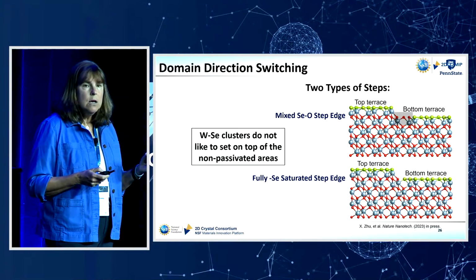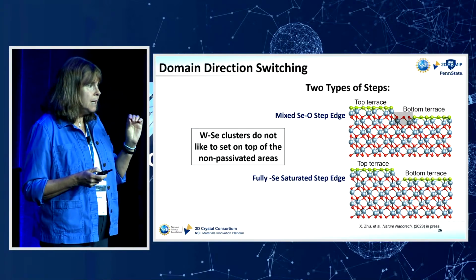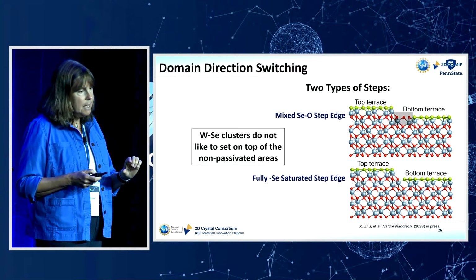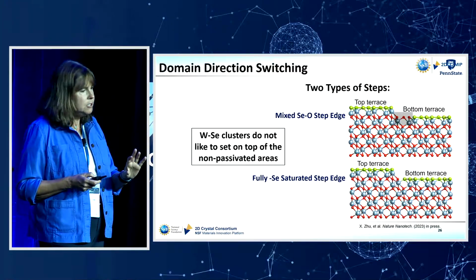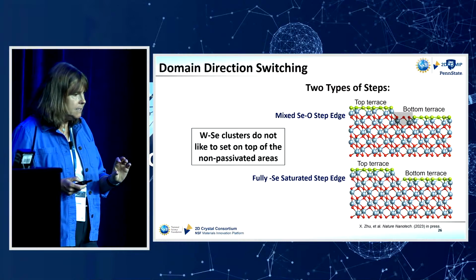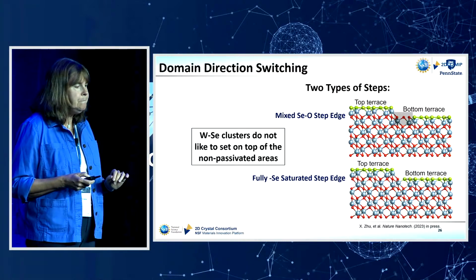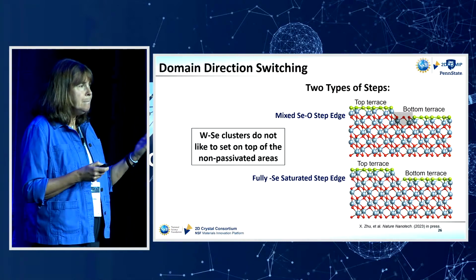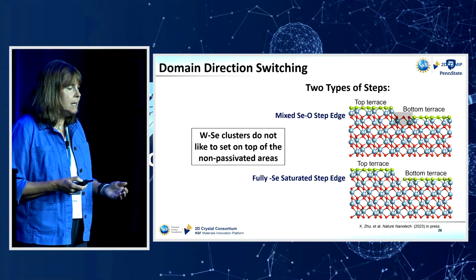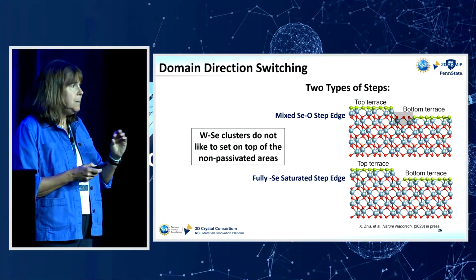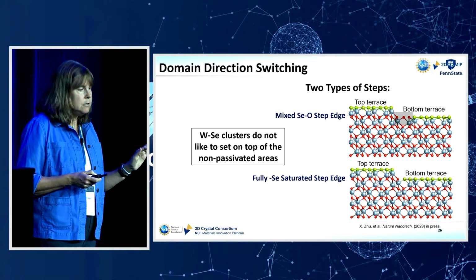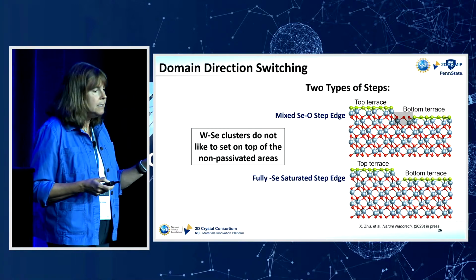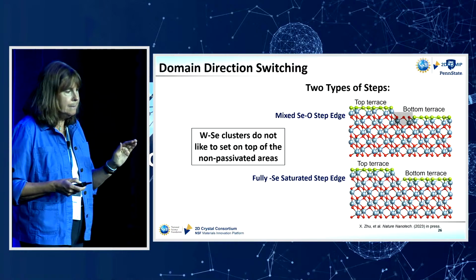In one case, we have not completely removed the hydroxyl groups from the bottom edge of the step. So there's still this oxygen remnant at the base of the step, the bottom edge of our step. So we call that a mixed selenium-oxygen step edge. In the other case, we have completely removed all the hydroxyl groups, and we have a fully selenium terminated step.